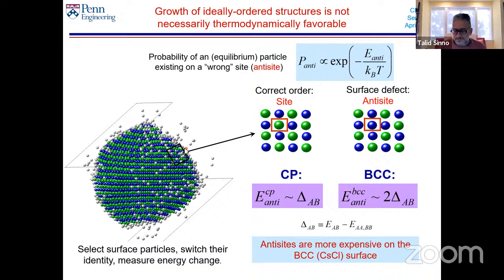So you can think that there's an energy penalty for forming such a defect, and there is. And we can calculate what the energy penalty is on the surface of an FCC, or a close-packed crystal. And I can do the same calculation on the surface of a BCC, or a cesium chloride crystal. And it turns out that the cost of forming an antisite defect is higher on the cesium chloride, or on the BCC, than it is on the close-packed crystal. And what does that mean? It just means that thermodynamically, you'd expect the cesium chloride to grow more ordered, because the cost of forming a defect is higher. And the lower the cost of forming a defect, the more defects you will have as this thing grows.